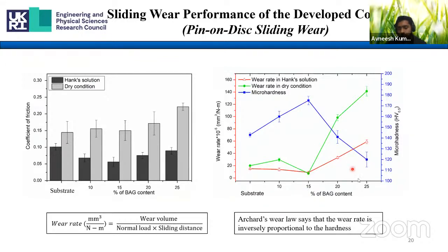It is because maybe as baghdadite content increases in the feedstock, it also influences the bonding between the particles, like between baghdadite and titanium, because it will interact with the titanium particle also, and it will affect the impact velocity of those particles. So further the deposition will get affected, and the cohesion strength of the coating will also get affected. So that can be the reason for the decrease of this microhardness value.